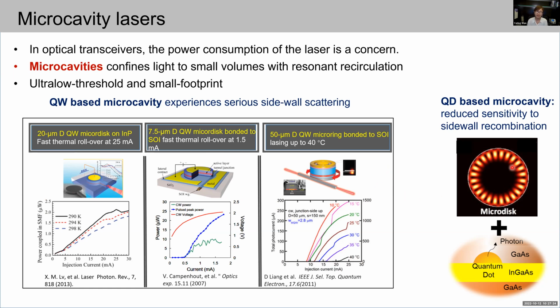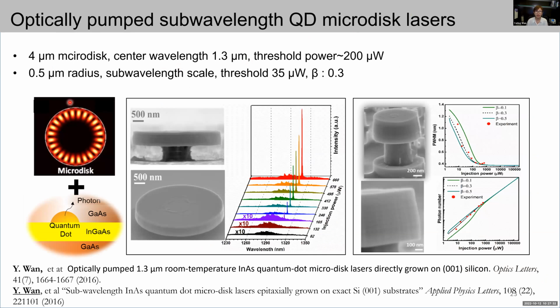Quantum dots, on the other hand, have reduced sensitivity to recombination at device sidewalls and other surface defects. So by combining the whispering gallery cavity with carrier localization of quantum dots, the optically pumped device can have a size as small as 4 micron in diameter and a threshold as low as 200 microwatt, and it can be scaled to subwavelength size with cavity size as small as 0.5 micrometer in radius, threshold as low as 35 microwatt, and a spontaneous emission factor as high as 0.3.